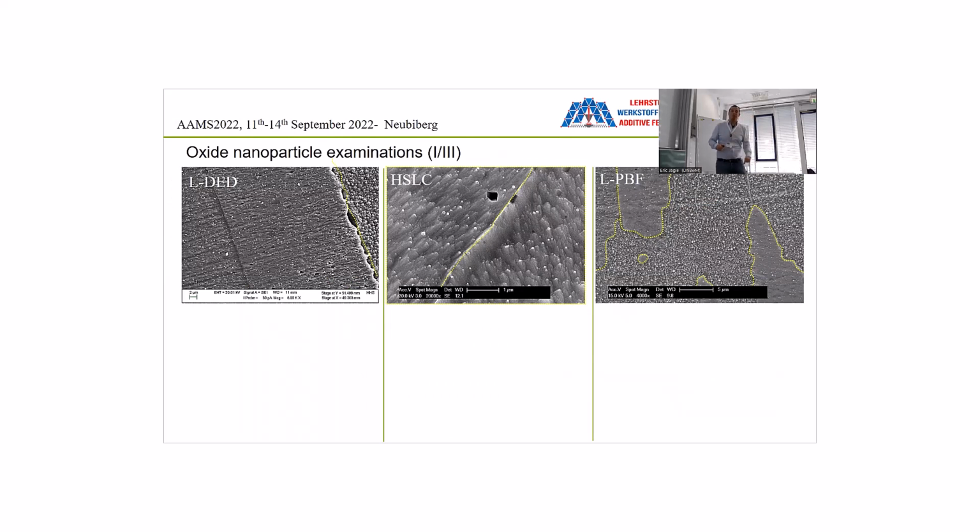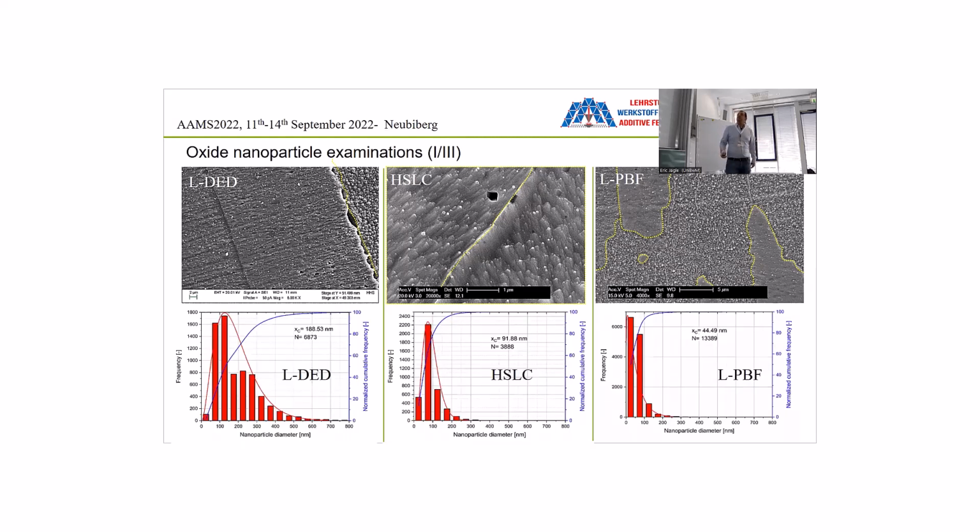Having a look at the microstructure, now we're looking at the oxide particles, which are the most interesting one. So you see here the nanoparticles. Judging from these pictures, you can always say, fine, it works. So we can disperse the oxide nanoparticles, which appear here as white spots. These are etched SEM images. So it works, it's nice.